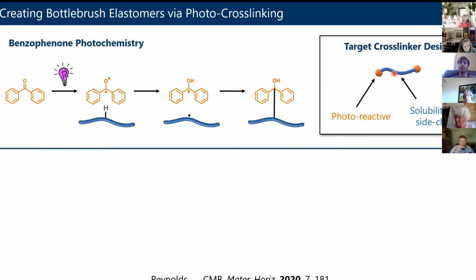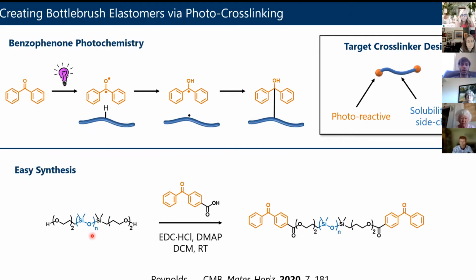Second, we thought it would be important to bridge these reactive benzophenone groups with something that will allow the crosslinker to mix well with the viscous liquid that's the Bottlebrush polymer. So you can imagine if the Bottlebrush polymer is mostly polydimethyl siloxane, why don't you make that linker in the crosslinker also polydimethyl siloxane? Those two things should dissolve in each other. And indeed they do. So we purchased polydimethyl siloxane, this time with 2 reactive chain ends. There's a hydroxyl group on the left and on the right. And we can do the same kind of linking chemistry with a functionalized benzophenone to simply install it on both sides of the PDMS chain.